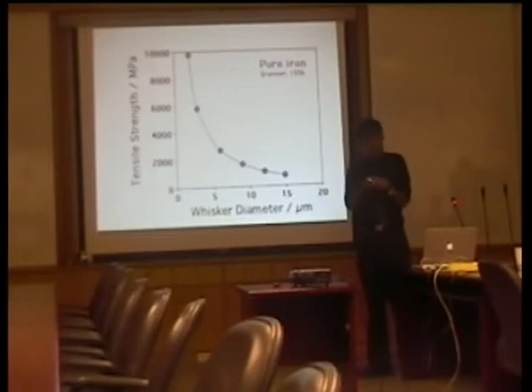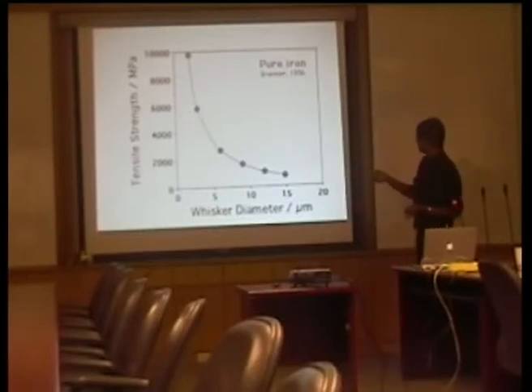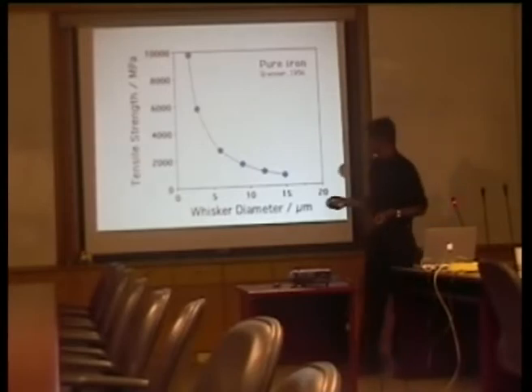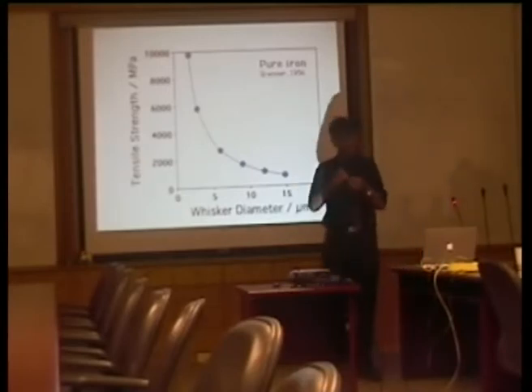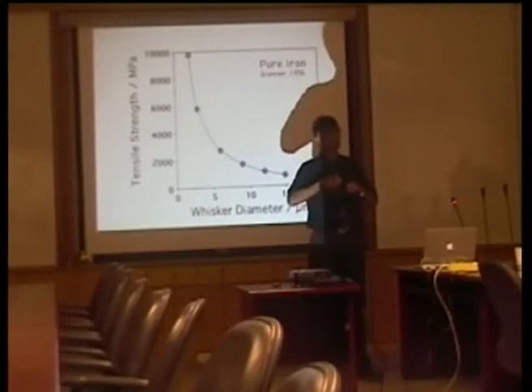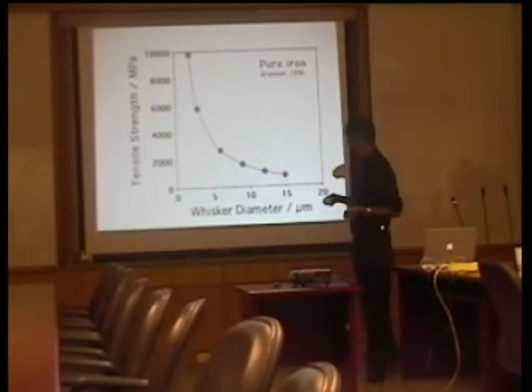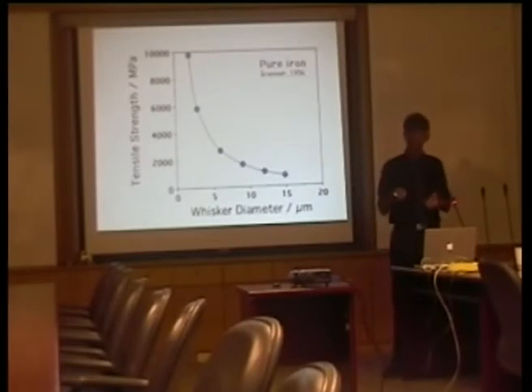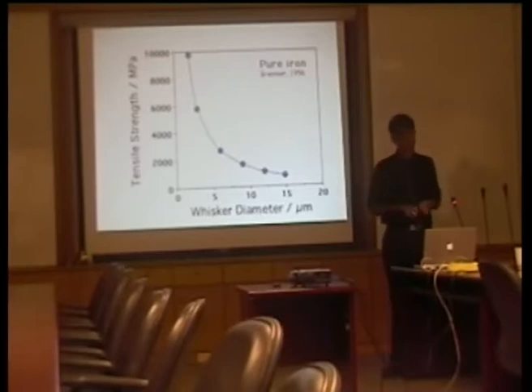But unfortunately, as you increase the size of the crystal, the strength collapses. Because in this case, the strength is coming from the fact that there are no dislocations in the material. So you have to really pull the atoms apart to break the crystal. As soon as we make the crystal large, the probability of getting defects increases, and therefore the strength collapses towards the normal strength levels that we see in iron.